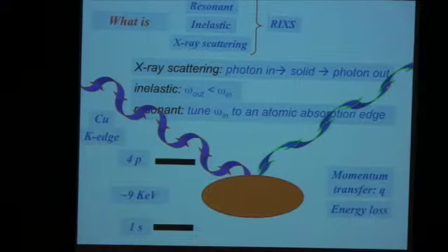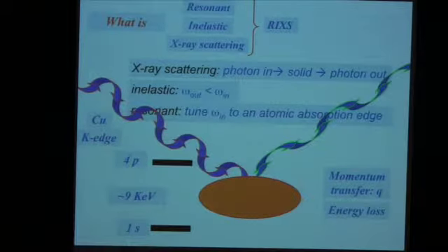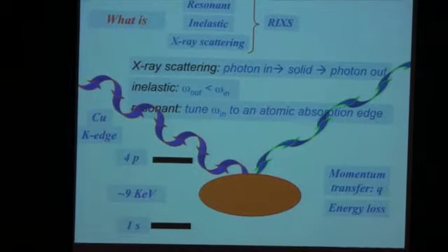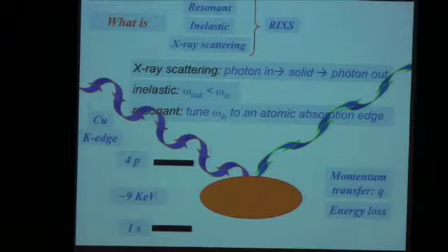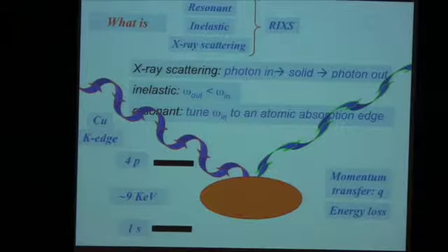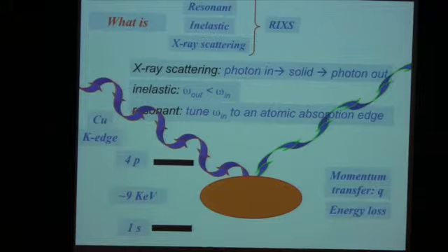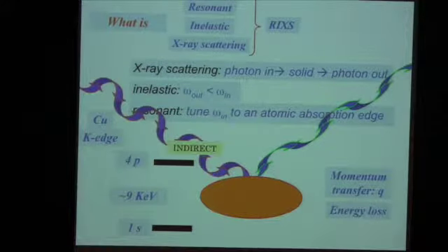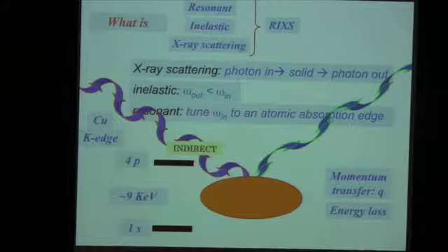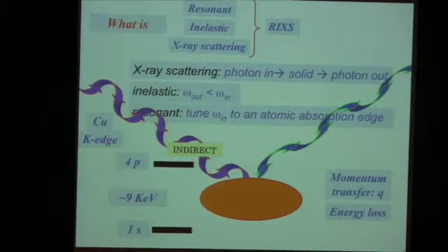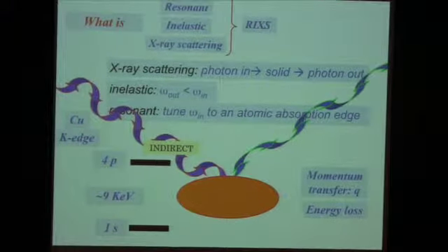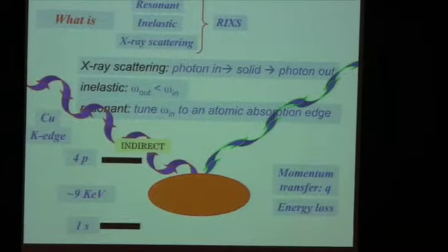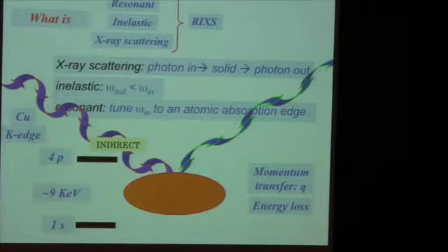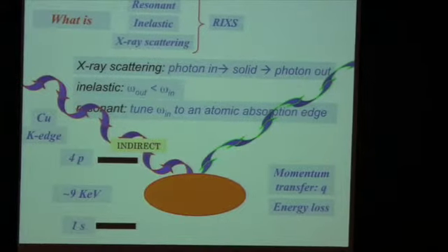After decay of this 1s-4p exciton, an X-ray photon is emitted, and the system is left behind with some finite momentum and some energy that the X-ray photon has lost to it. Now, this is the K-edge, and at the copper K-edge we talk about indirect RIXS. Why? Because these 4p levels are rather high above the Fermi level, and you do not directly probe the excitations of the electrons around the Fermi level.